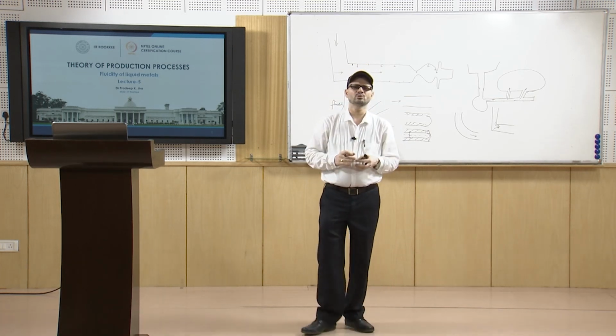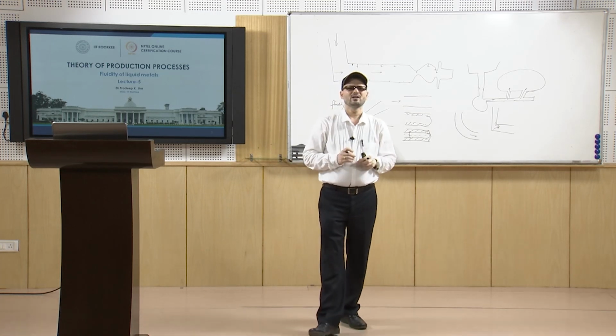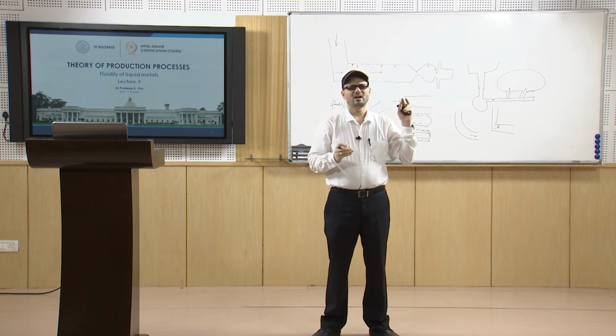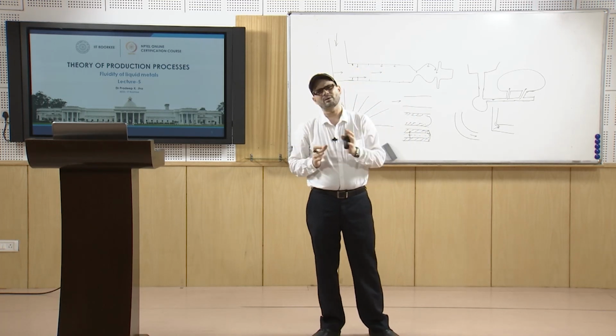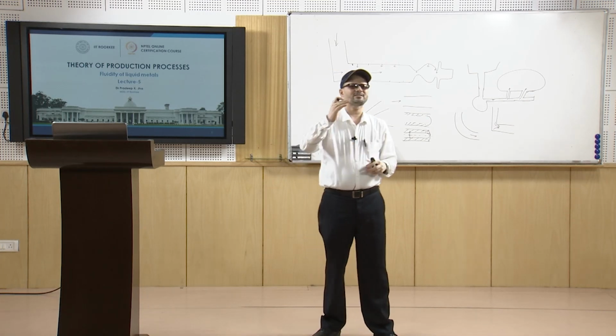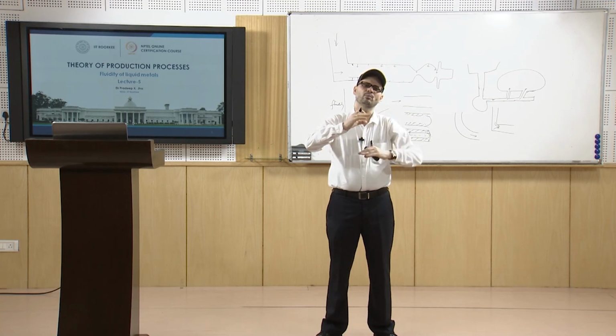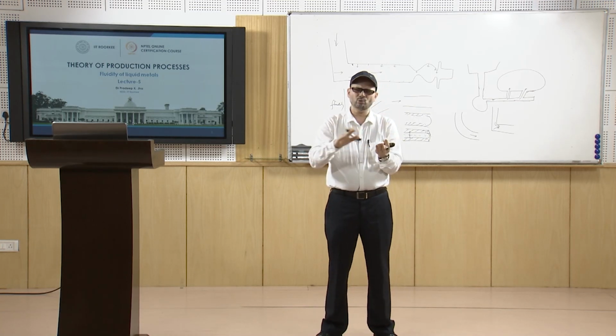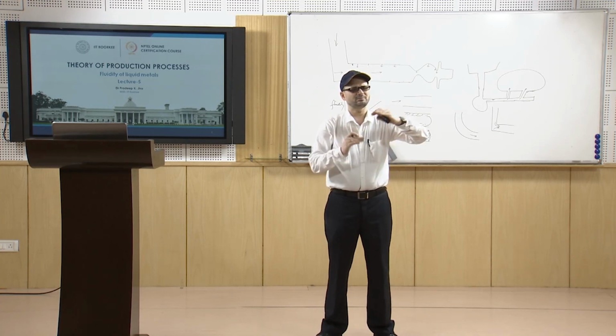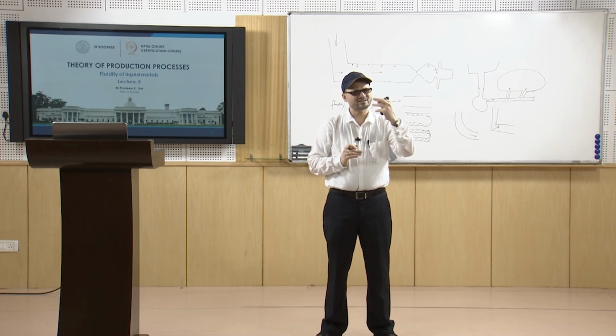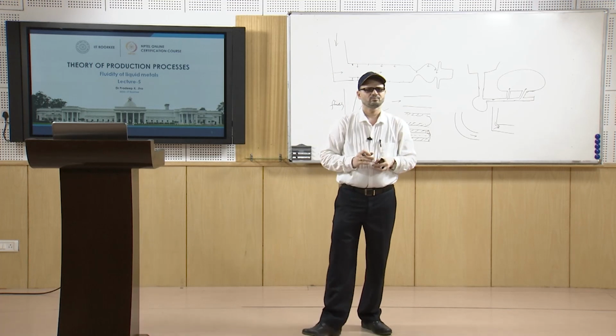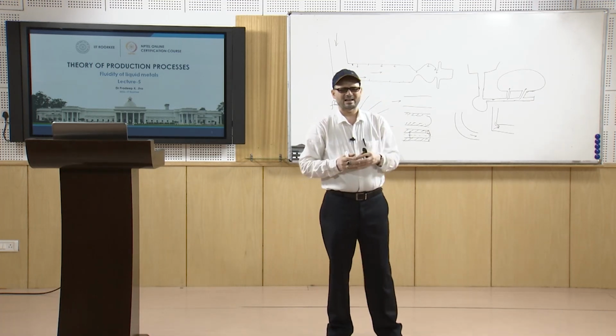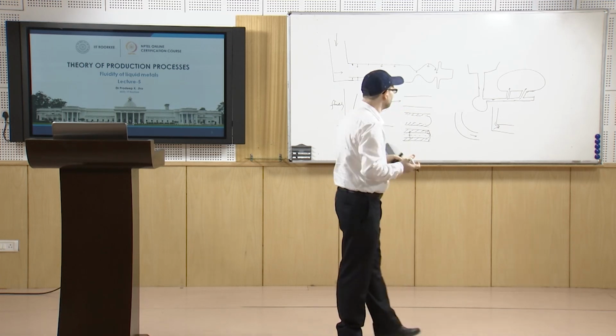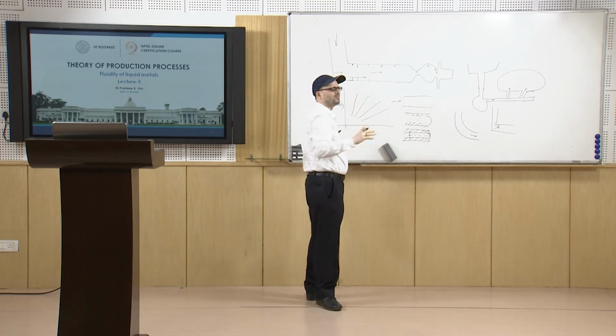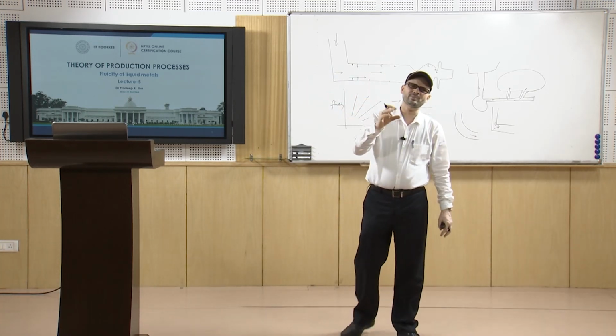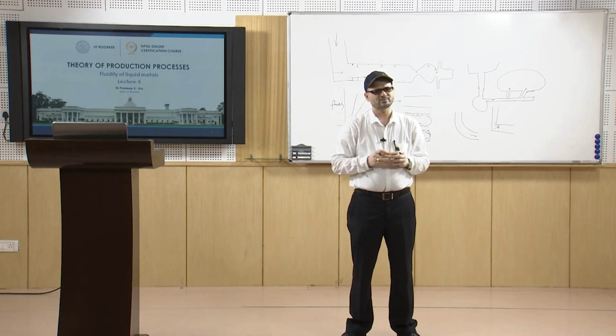Other factors are mold related factors we discussed earlier, that you have molding sand and binder. The molding sand which is used, you must have fine sand, which decreases the resistance and gives less resistance to the metal which is flowing. Similarly, sometimes we give the mold wash so that you have a smooth surface on the molding sand which is in contact with the liquid metal, and that provides less resistance to the metal. Then you have mold temperature, as we discussed. Most of the superheat is arrested when the liquid metal touches the mold, and the mold is normally at room temperature.